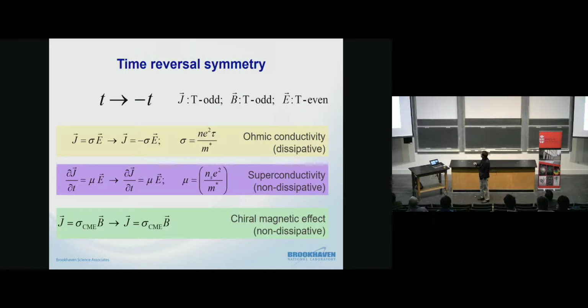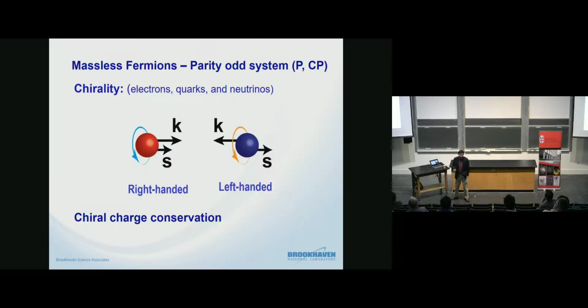If we look at the first London equation, it does not. This is invariant under the time transformation, and it's non-dissipative. And if we do the chiral effect the same way, it does not break time reversal symmetry, so this one is not dissipative. Now how are we going to get it? I told you that you need left-handed and right-handed fermions. These come from the high-energy nuclear physics world. They are called massless fermions, and they actually appear in those Weyl semimetal systems.